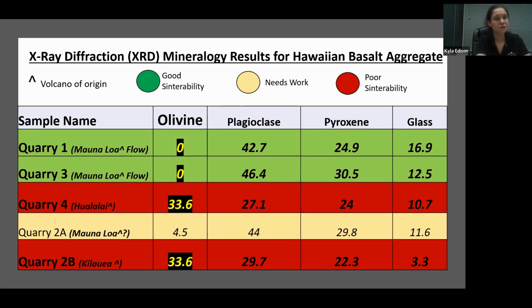And so looking at the XRD analysis, you'll see that Quarry 1 and Quarry 3 have 0% olivine, where that's not necessarily true. There is olivine in these samples. The amount of olivine that's in it is just about negligible. We're not finding olivine within the matrix of this stuff. We're just finding little pieces of olivine here and there. So basically the olivine content in these two materials is extremely low.